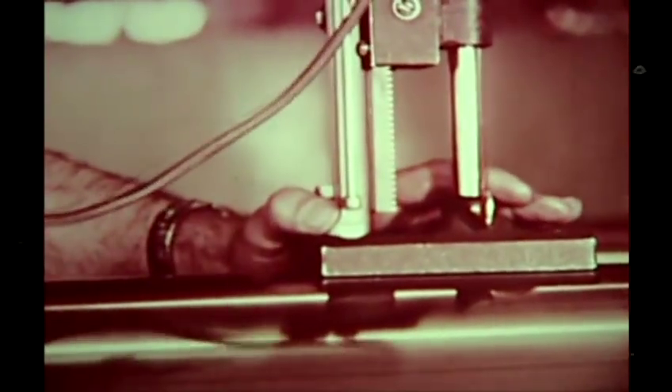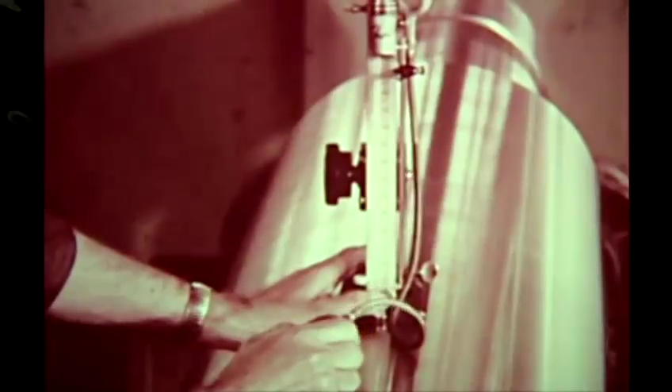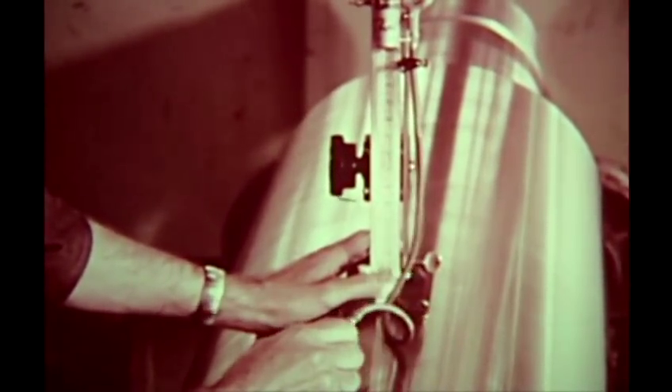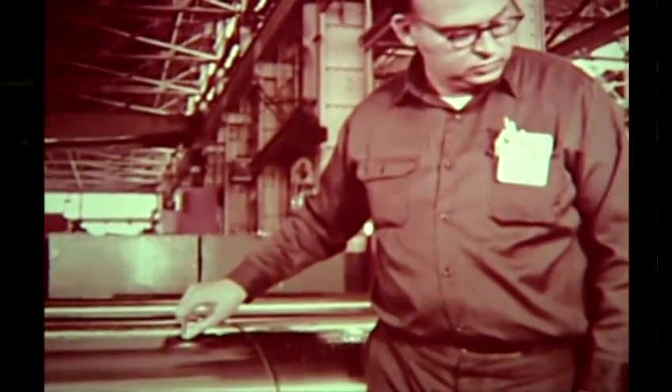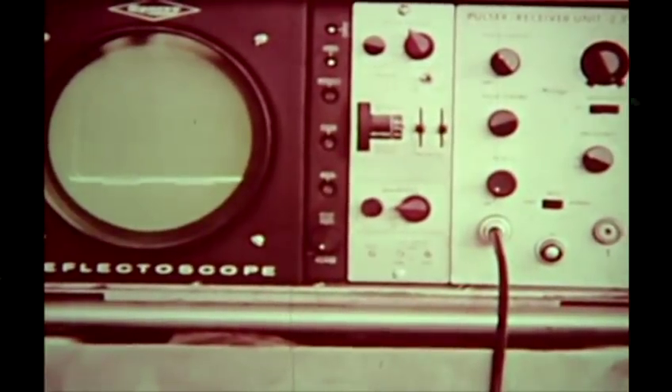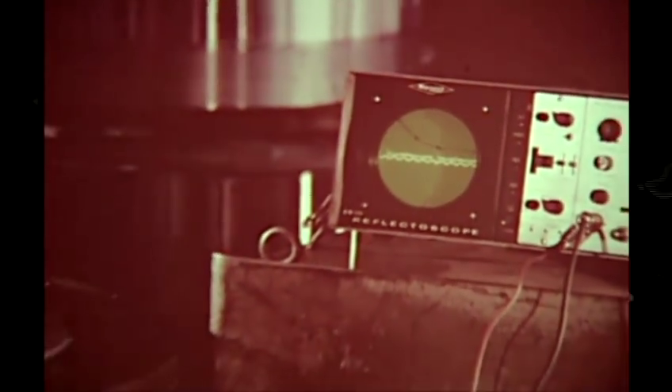This large roll for a steel rolling mill is being surface hardened to desired characteristics and hardness profile. Finished rolls, as with all forgings, are subjected to a series of quality control tests. This scleroscope hardness test assures that the surface of these rolls meets required specifications. But the area below the exterior surface also undergoes quality tests — ultrasonic test equipment assures consistent metal composition and freedom from internal flaws. Wherever industry demands ultimate quality, such programs of quality control ensure that open-die forgings represent the highest standard of reliability.